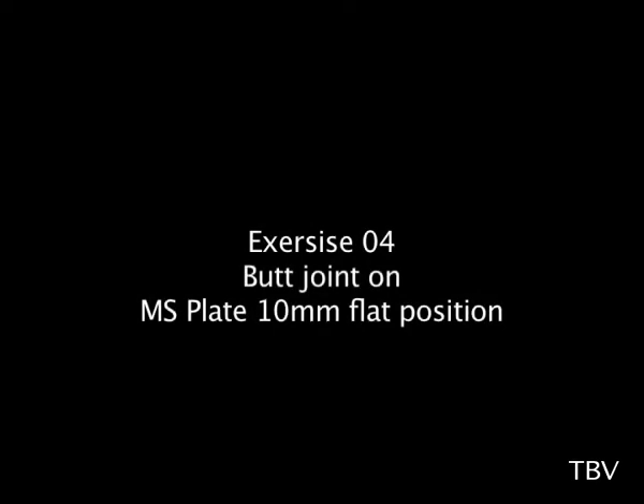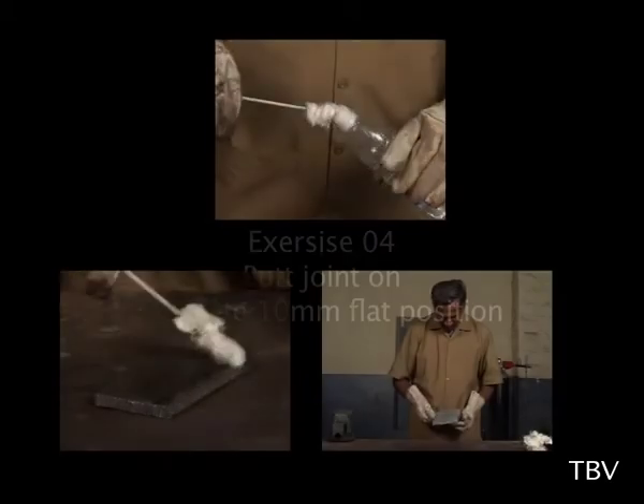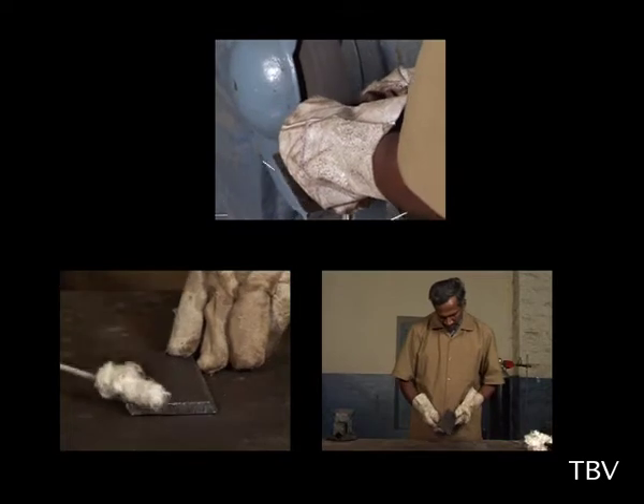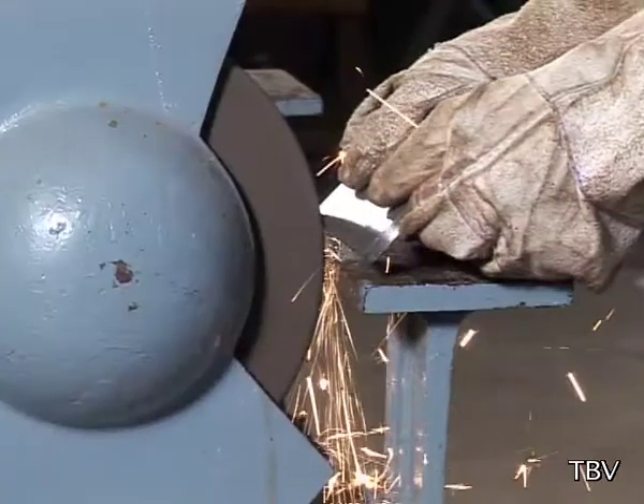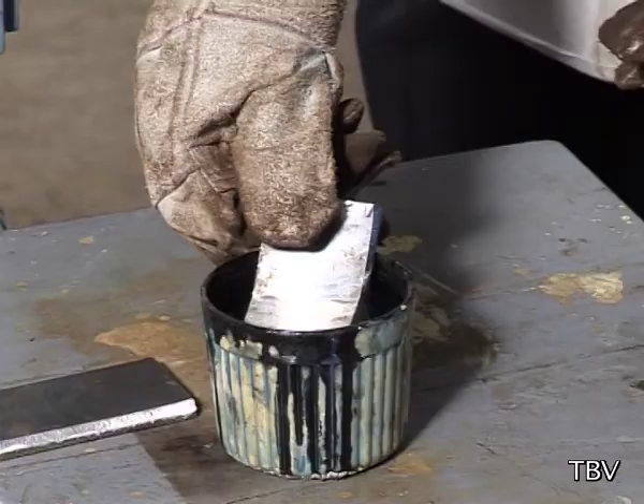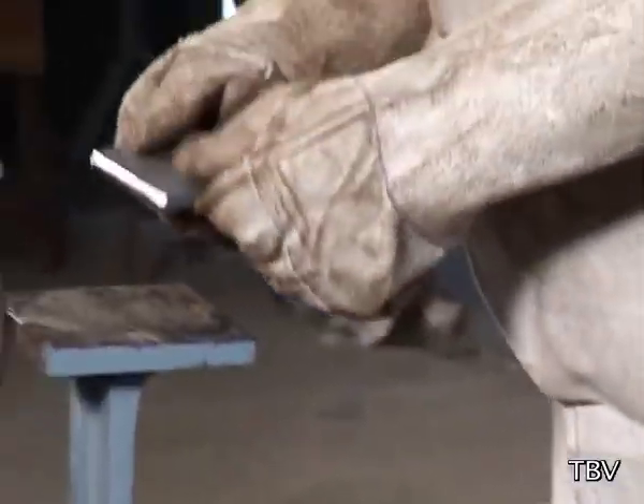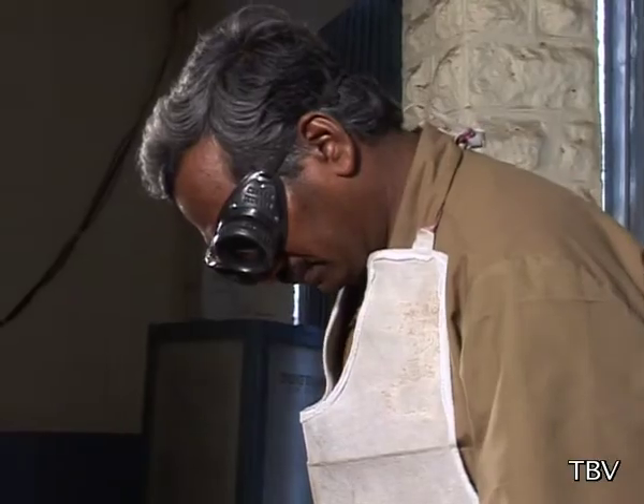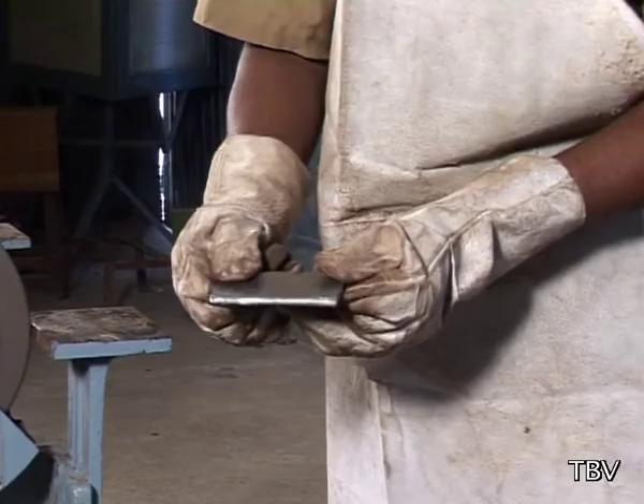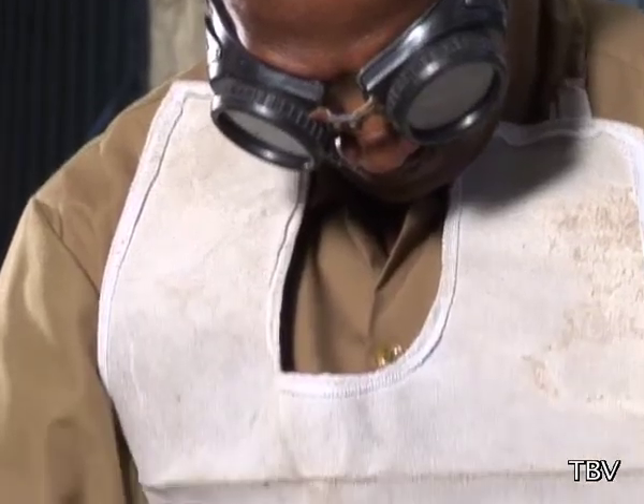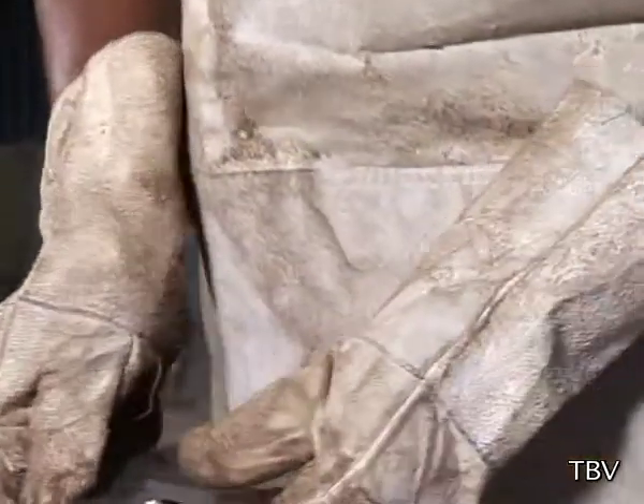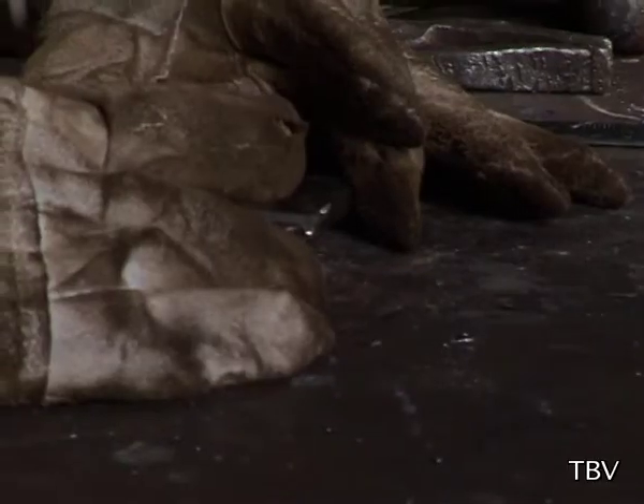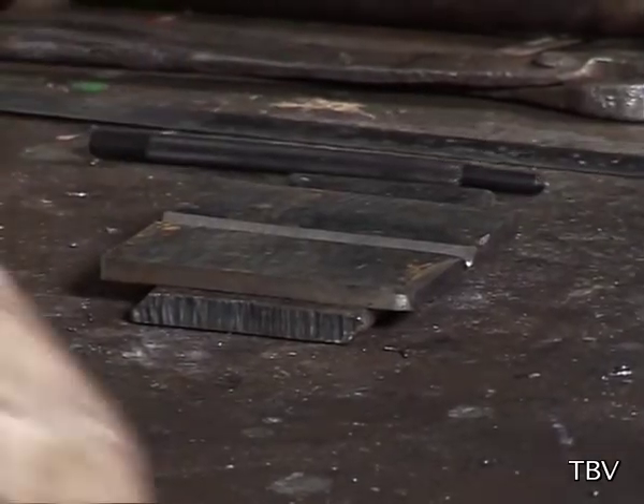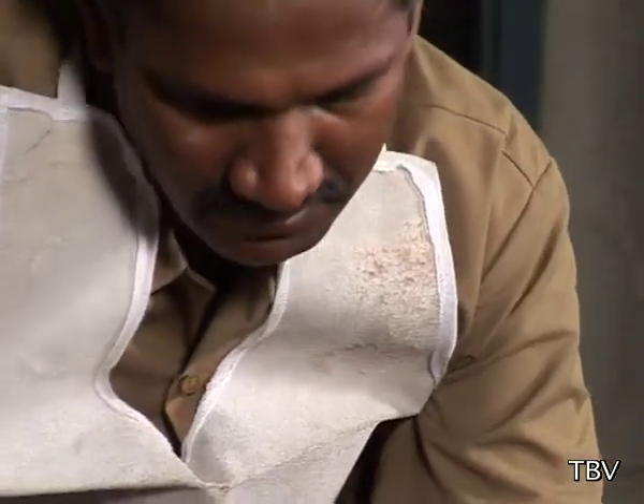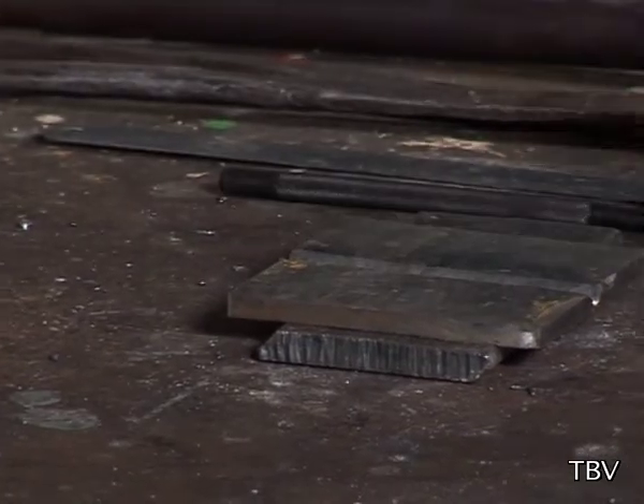Exercise 4. Butt joint on mild steel plate of 10 mm in flat position. You have already seen the preparation of the jobs. Groove or file a 1.5 mm root face on each bevel as shown. Now, the workpiece is ready for welding. 0.8 mm diameter wire is used for welding. The procedure for CO2 flow into the heater and the welding gun is the same as observed earlier.